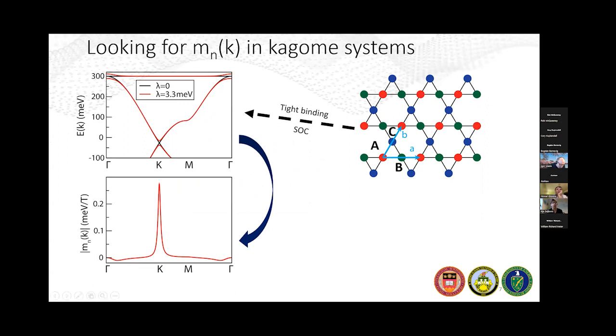And I just want to go over this very briefly. I know this is very familiar for the audience, but on the left here, I'm showing a simple electronic band structure of a kagome system. So it's a single kagome plane, and from tight binding calculations, one can see that the electronic band structure consists of Dirac points at K. There's going to be a van Hove singularity at M, and there's also going to be a flat band at the top, or I guess at the bottom of the dispersion, depending on the details of the system.